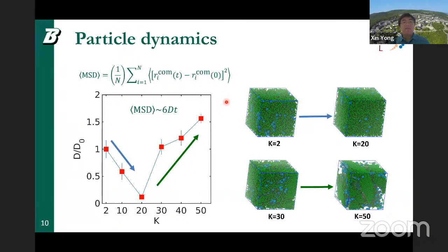So then we're looking at the particles inside this system. What's their diffusion? What's their dynamics? So we quantify the mean square displacement of these particles, and we find that in general, on long-time scale, the particles diffuse normally, so they dynamically exhibit normal diffusion. And so we can extract the diffusion coefficient by fitting the MSD on the long time scale.